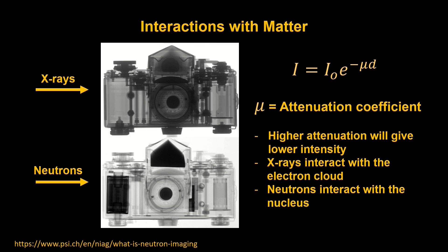And the thing that sticks up the most is the triangular piece and that cylindrical piece over to the left, which don't really show up in the X-rays at all, but have a very high contrast in the neutron image. This is likely because these materials are made of plastic, which is hard to show up in X-rays when you have metal components as well. But also hydrogen abundant, which makes it highly attenuating to neutrons.